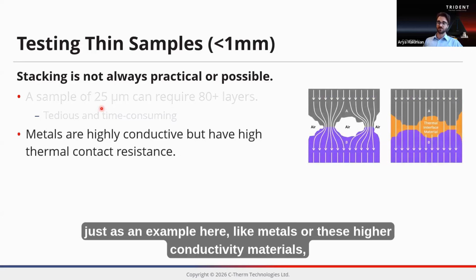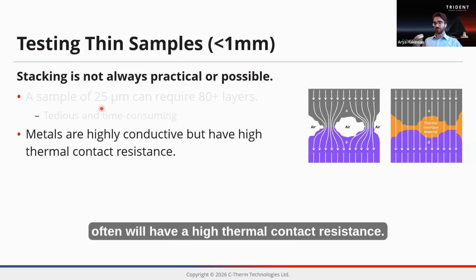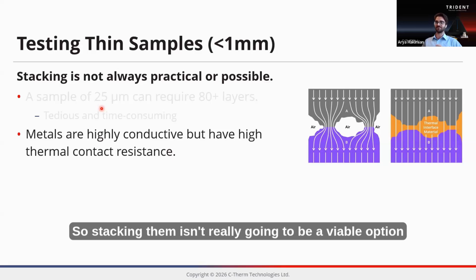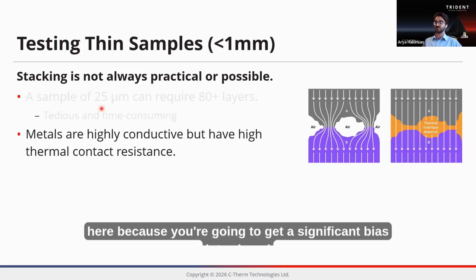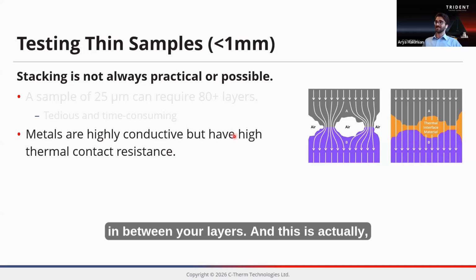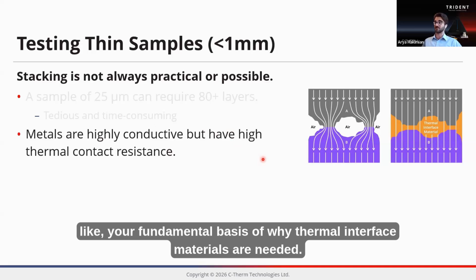One sample type, just as an example here, like metals or these higher conductivity materials, often will have a high thermal contact resistance. So stacking them isn't really going to be a viable option here because you're going to get a significant bias introduced in between your layers. And this is actually the fundamental basis of why thermal interface materials are needed.